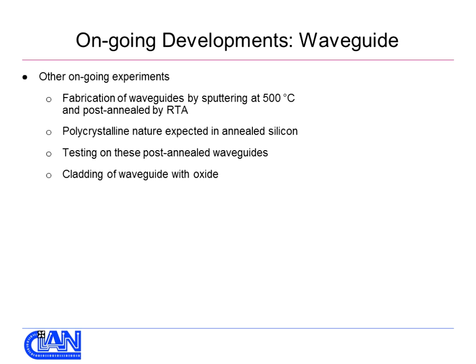And we can test this individually. So first, we can sputter at 500 degrees with no annealing, sputter at room temperature and then anneal afterwards, and then combine the two. And we hope to do that within the near future to see what kind of differences we see experimentally. Is one more effective than another? We're not quite sure yet.